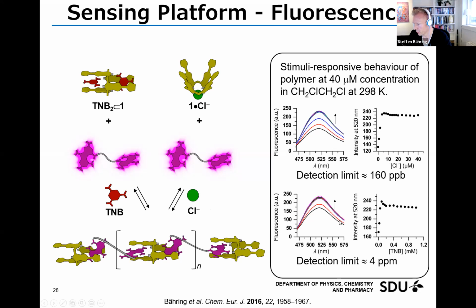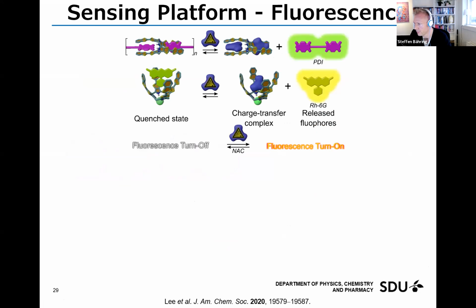But in the example with the TNB, we have a slightly less fluorescence increase when we add in TNB, but you can still see clearly here that it increases, but then it stabilizes. So we don't get a further fluorescence turn on. So this was in 2016, and then following this work, we recently reported different types of indicator displacement assays where we used the benzo derivative of the TTF Calixpyrrole and different types of fluorophores.